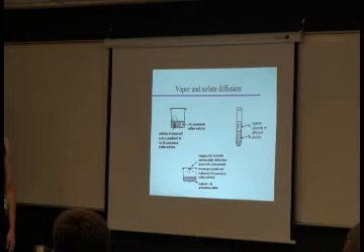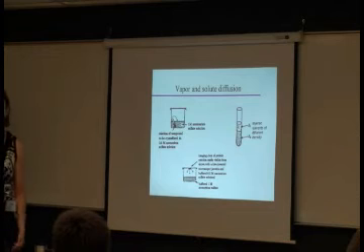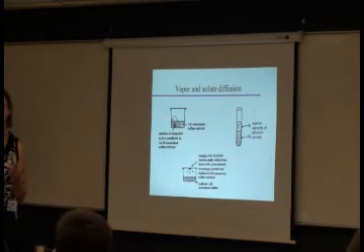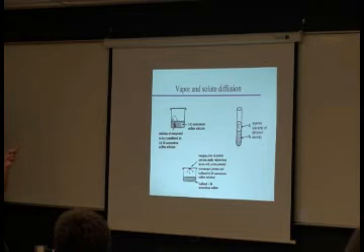Well, this system isn't really at equilibrium if you think about it, right? We have a more and a less concentrated solution. So what will slowly happen is the two solutions will try to be at equal concentration. So some of the water in the less concentrated solution will evaporate and go into the rest of the solution. Well, that is just very slow, very controlled evaporation of your solvent. Okay? So if normal evaporation of the water is too fast, this may be a setup that helps.